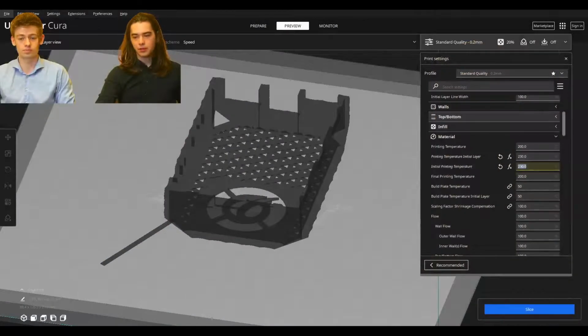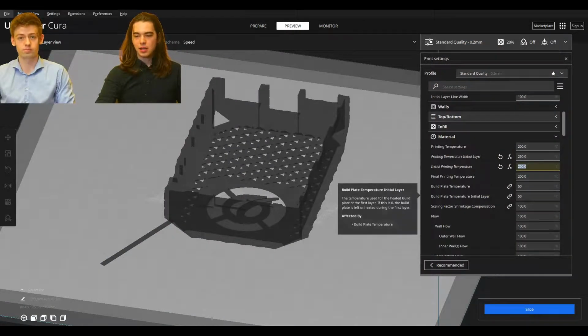Exactly. So you're not getting a correct reading, and a really good way that I would recommend for things like glass beds is to set the initial layer build plate temperature a little bit higher, because if you're aiming for a 60-degree bed, you might want to set it to something like 65, because by the time the thermistor on the bottom of your bed hits 65, the top of the glass should be around 60.